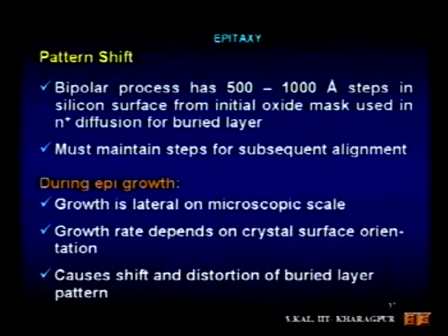As a result, before epitaxial growth, when you remove the complete oxide, then in the buried layer portion also the oxides are removed. And at those particular positions where buried layers are located, silicon will be consumed more, so it will be etched. As a result, a depression is formed in the buried layer region. That depression will continue into the subsequent epitaxial growth process, and epitaxial growth is a lateral growth, as you have seen. Although thickness increases vertically, laterally it grows layer by layer: first one layer, then the second, then the third, like that. In this way the buried layer pattern will be shifted from its original position. That is known as the pattern shift.